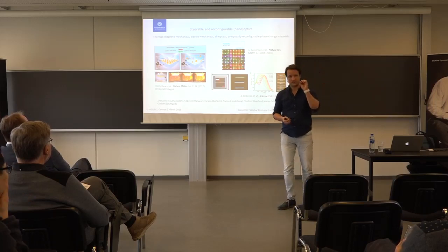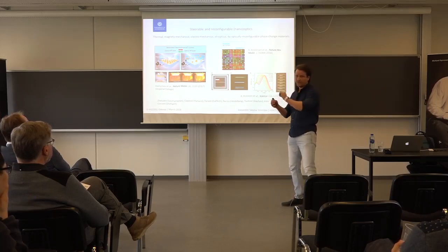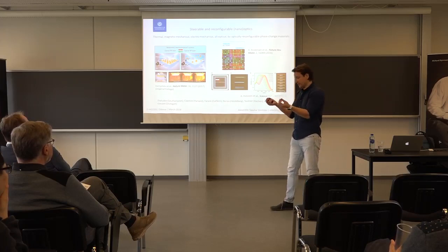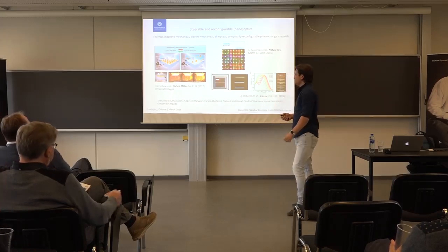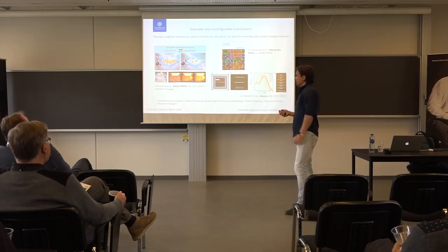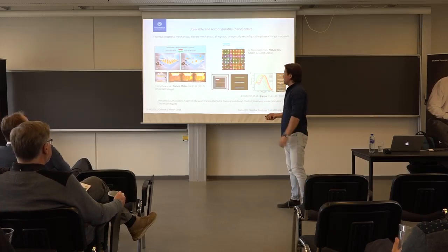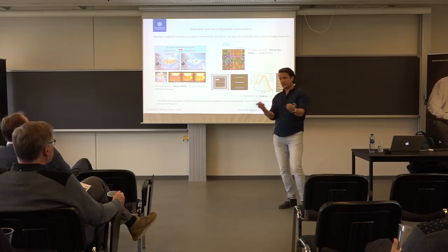So small particles of silver or gold can scatter selective wavelengths, can absorb selective wavelengths, and that's why you can see these vivid colors that never fade, because the particles are embedded into the dielectric matrix of the glass, that we did in the Middle Ages. So the idea is that these particles readily work with light. They're on the size of some nanometers, maybe 50 nanometers, and the way they couple to each other also influences the way they interact with light.